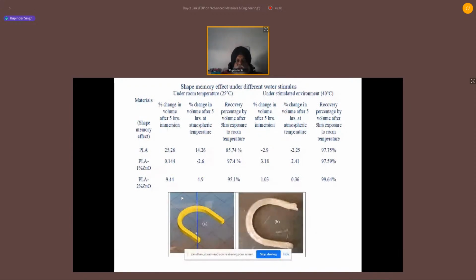So what we observed, once we made this type of U, I put it in water for 5 hours at a temperature of 25 degrees Celsius, and then after 5 hours we removed it and tried to see what the recovery is. With the 1% ZnO, the recovery was 97%, meaning the U becomes a V, and once you put it for some period, it again regains its position, right?